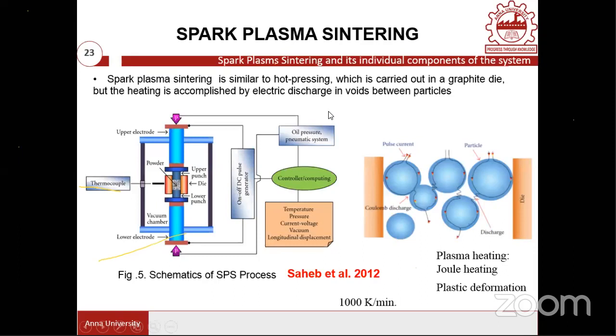Therefore, here we have used spark plasma sintering, where the material is loaded in a graphite die, and you can apply a pulsed DC current and also pressure, 50 MPa pressure and pulsed DC. Because of the plasma heating of the surface of the powder particles, there will be heat generation, and also Joule heating because of the pulsed DC current, and also plastic deformation because of the pressure application, which creates more densified components. Because this process finishes quickly, there won't be much possibility of grain growth. Therefore, whatever problems you have with the conventional sintering technique, like differential densification, nitrogen evaporation, as well as grain growth, everything will be stopped here.